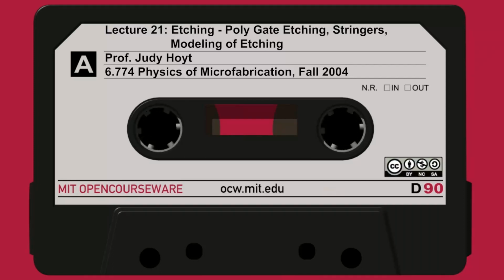This particular paper, which I took from a few months ago at the VLSI conference in Hawaii, was showing that nickel silicide works much better for fully siliciding than does cobalt silicide, which leaves behind voids. So there's an example. Not only are we etching polysilicon gates these days, we may end up siliciding them completely. That's what people are considering. There's another type of process which I'm picturing here on the lower left, called a Damascene replacement gate process. And here's an example of a gate where I have titanium nitride.